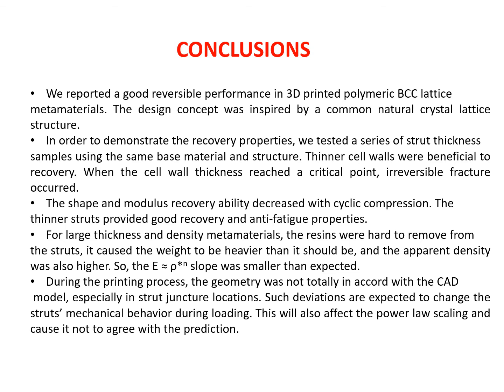In order to demonstrate the recovery properties, we tested a series of strut thickness samples using the same base material and structure. Thinner cell walls were beneficial to recovery. When the cell wall thickness reached a critical point, irreversible fracture occurred. The shape and modulus recovery ability decreased with cyclic compression. The thinner struts provided good recovery and anti-fatigue properties.